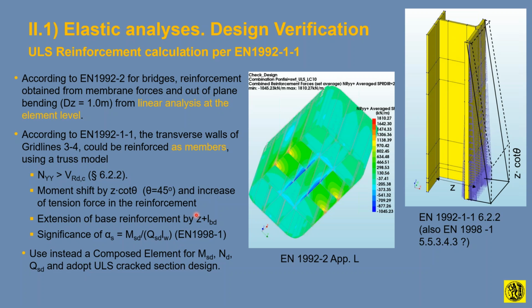So, of course, we can do more because we can either reinforce this as a beam with horizontal stirrups. In fact, if you go to Eurocode 8, which is, I don't know, Eurocode is seismic, of course we use it, but they even give you some additional measures of how to develop the ultimate limit state beam reinforcement of this wall, and then use a good percentage of this horizontal reinforcement vertically in this area here, because these two directions interact under the 45-degree crack, and both directions pretty much have to accept this factored shear force.